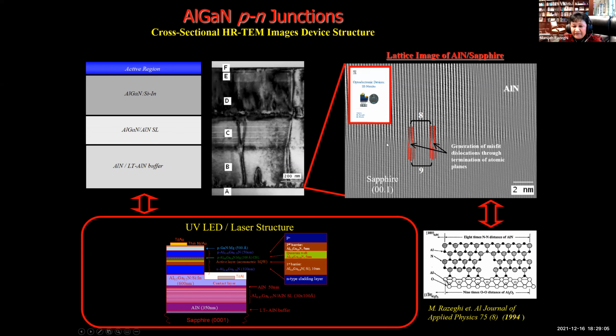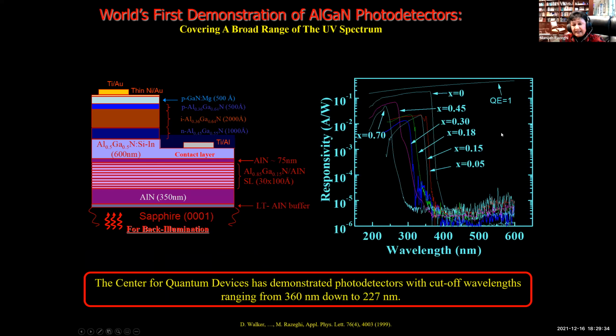If you can see, every 9 planes, we have 1 edge dislocation. The rest is perfect. That's the substrate, and that is the epi layer, and there are areas where you cannot have any defect. So you can make any device on this material, and now we came with the UV LED and at the same time the detector.